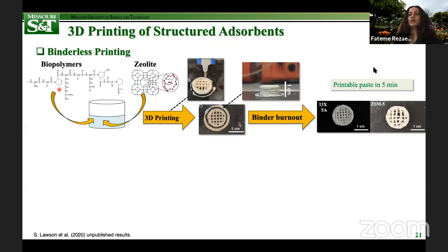The first step in 3D printing binderless zeolite scaffolds lies in the selection of suitable binding agents. Why is this important? Because producing 100% pure monoliths necessitates that the binder be completely organic, so that it can be removed during calcination, as well as capable of achieving a favorable rheology. Rheology is very important, otherwise the paste cannot be printed. What we found was that biopolymers such as gelatin are suitable candidates for this purpose. Another advantage of this method is rapid preparation and simplicity. It requires only 2 steps to prepare structured adsorbents.